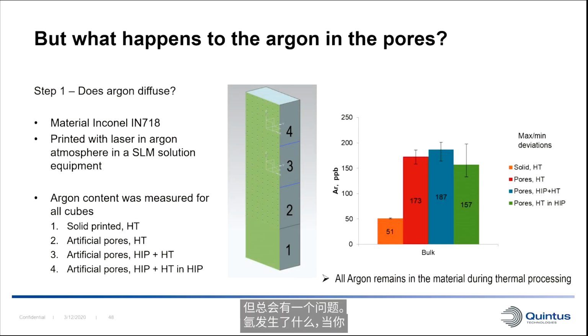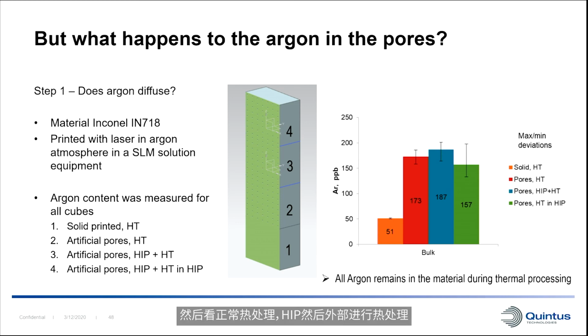But there's always a question that comes, okay, what happens with the argon when you print on purpose with some porosity? Well, we've done some work on this as well. So here's some recent results that haven't been published yet, but I think this is the first time we show these now. But we printed 4 cubes, one with the normal solid printed parameters. In this case, it's Inconel 718. And we've also then printed with artificial pores to trap some argon on purpose.